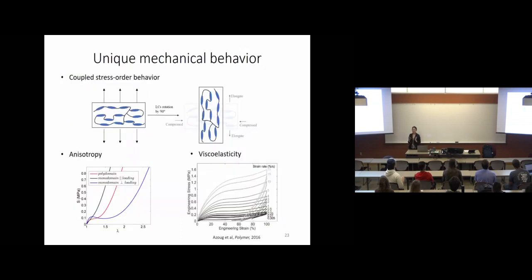Liquid crystal elastomers have very unique mechanical properties. The most interesting thing is their stress and order coupling behavior. If you have a liquid crystal elastomer with a director aligned in a certain direction, but now you apply an external force which is non-parallel to the orientation, you can actually rotate the director towards the stretching direction, which can give rise to a large spontaneous strain. Because of this, they show anisotropic properties. If you stretch a liquid crystal elastomer in the parallel or perpendicular direction, you see very different stress-strain curves. Moreover, they also show high rate dependency. This is the viscoelastic property.